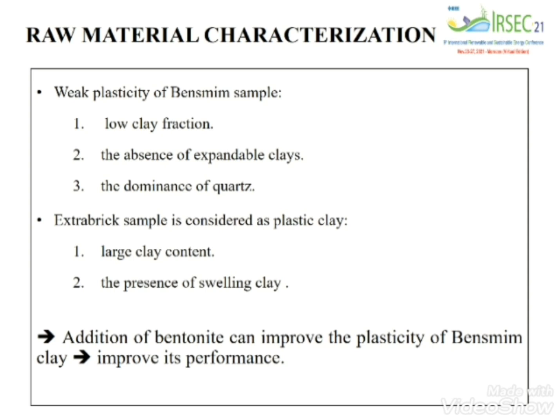From all the conducted tests, we can say that the weak plasticity of the Bensmim sample is related to its low clay fraction, the absence of expandable or swollen clays, and the dominance of quartz. However, the Extrabrick sample is considered a plastic clay because of its large clay content and the presence of swollen clay. From all this, we can suggest that the addition of bentonite clay to the Bensmim sample can improve the plasticity and thus it will also improve its performance.